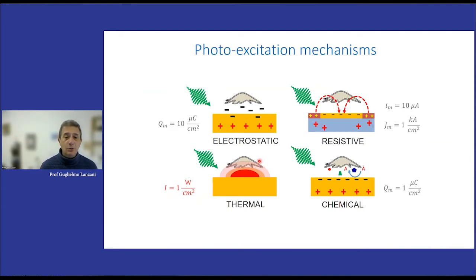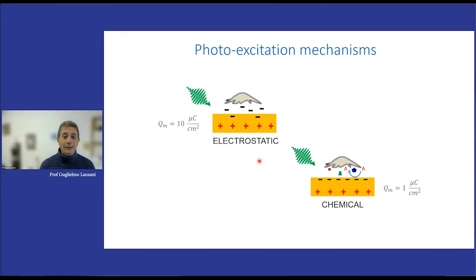The other thing that we can exclude is the resistive path, because we don't have enough current charge to support the current. We don't have a counter electrode. So we get rid of these two and we end up with these two mechanisms that probably are both playing a role: the electrostatic effect and the chemical effect.